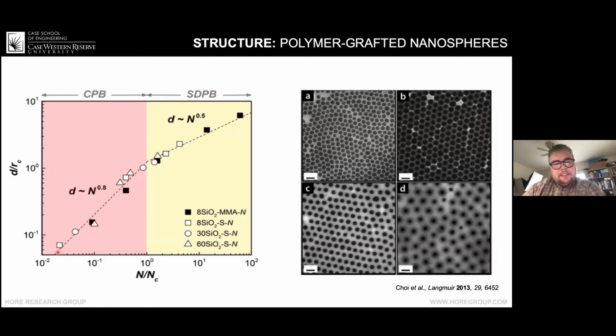But what you can see is the trends here: as you're changing the molecular weight, you can see the transition between the stretched and the unstretched regions. So if you wanted to get that transition point RC, this point right here is going to be RC. It's going to be that transition between the two regions. So if you were only doing light scattering, you could prepare all these molecular weights of the grafted particles, identify where RC is, and then from that you could calculate the thermodynamic properties.